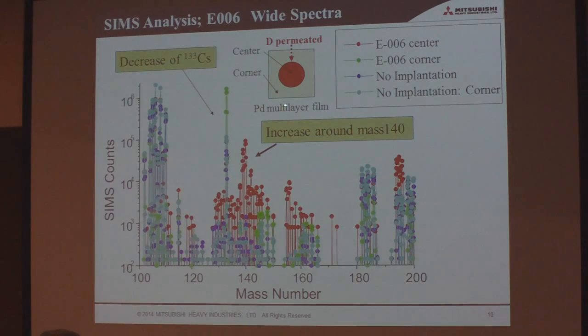At the corner, we can see cesium 133 has a very high peak. And at the center, the cesium decreases by about 1 to 2 orders of magnitude. And correspondingly, in the center region, we can see the increase of many masses, around mass 140.